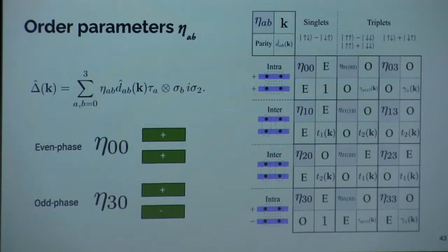If we didn't have an additional layer, then the only possible singlet would be what I call eta 00, which is an even singlet order parameter, where the order parameter has a plus sign on one layer and also a plus sign on the other layer. But since I have an additional degree of freedom, I also can have the same type of singlet, but where the order parameter has a plus sign on one layer and a minus sign on the second layer. Which one dominates is now, of course, an issue of analyzing the instability condition.